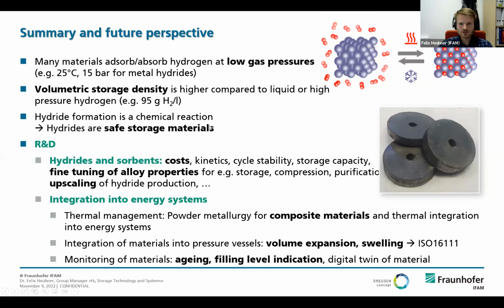Yeah. The reactions are safe because the hydrogen is bound on the materials, to have this link to safety again. And R&D is performed these days in terms of cost because cost of the materials needs to come down. Sometimes there are materials inside for catalyzing the reaction like vanadium, but there are some very low cost materials available like iron, titanium based alloys, for example, or manganese-based alloys. So this is very important to lower the costs here on a system level. Having a look at the same time on kinetics, cycle stability, storage capacity.